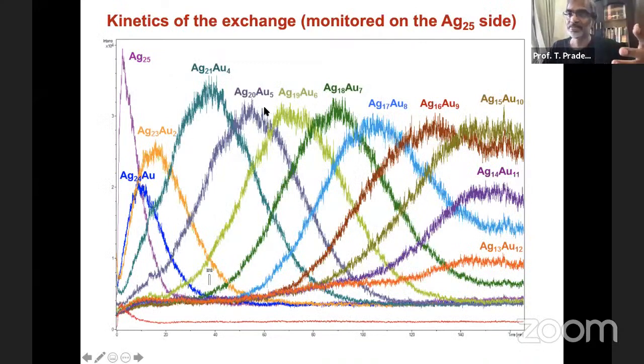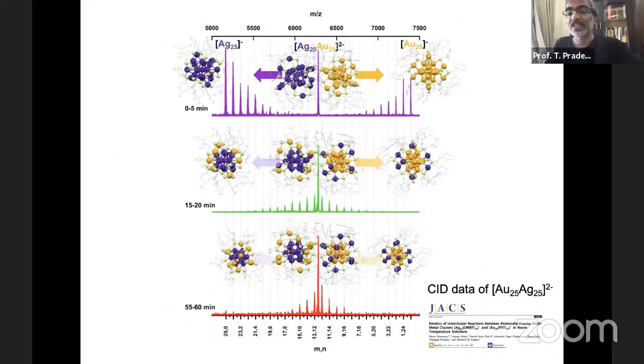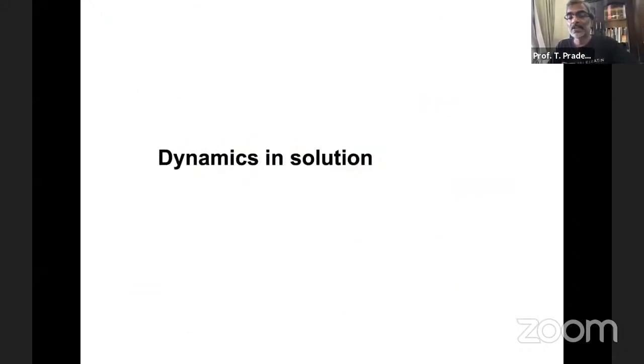This very interesting chemical evolution can be studied, and that gives you kinetics. This kinetics tells you that what is happening is very similar to a consecutive chemical reaction: A goes to B goes to C. A goes down, B goes up and then decreases, and C goes up. This is something that classical physical chemistry would model, and we can model all these chemical reactions happening in these.